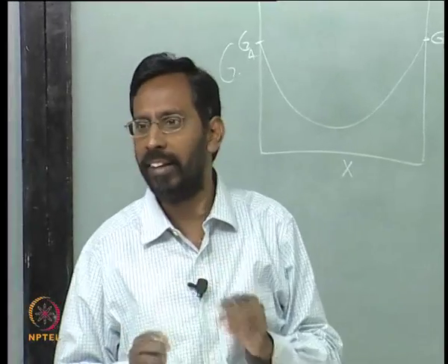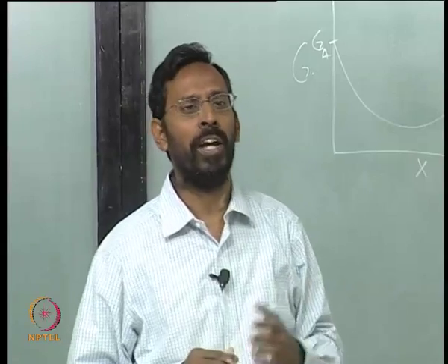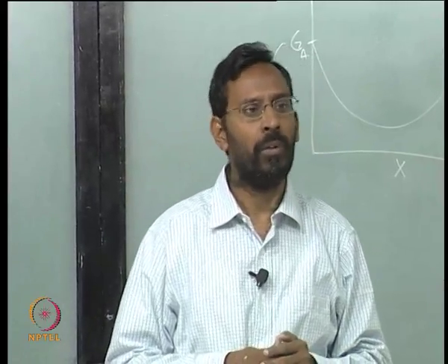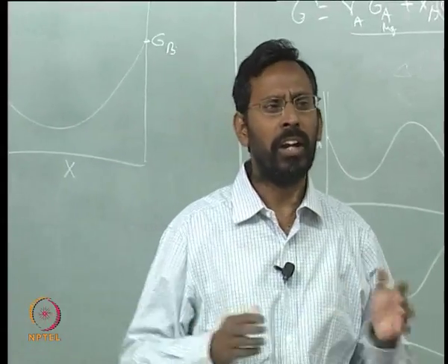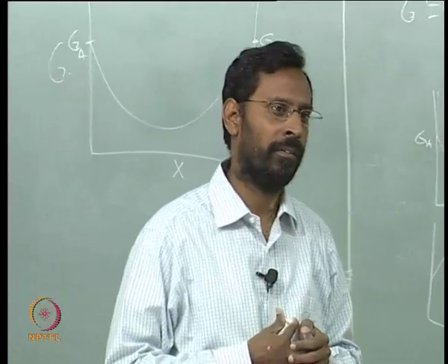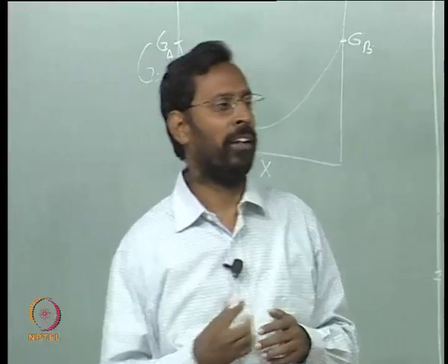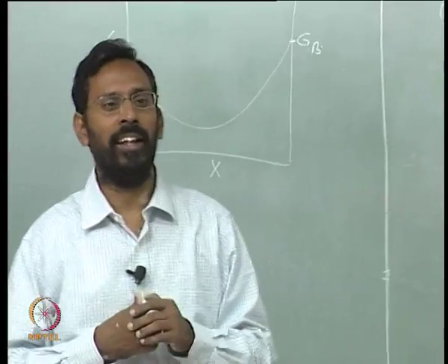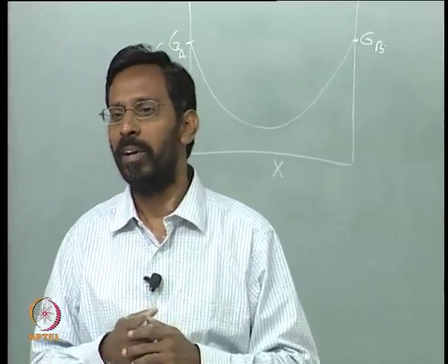And that is the reason why it is very difficult to purify a metal. You can talk about 4 nines, 5 nines, 6 nines, but you can never talk about 100% of A or 100% of B. And the more nines you want, the more difficult it is, because you are somehow pulling the system away from its nature.